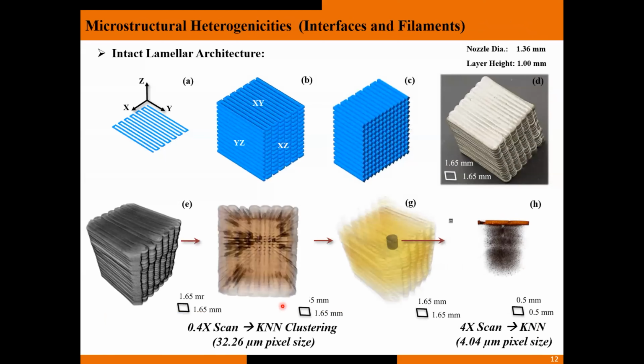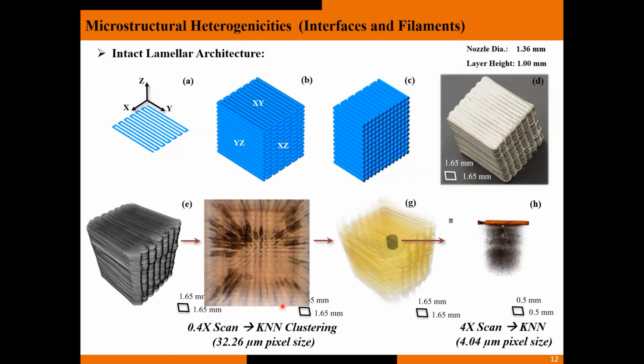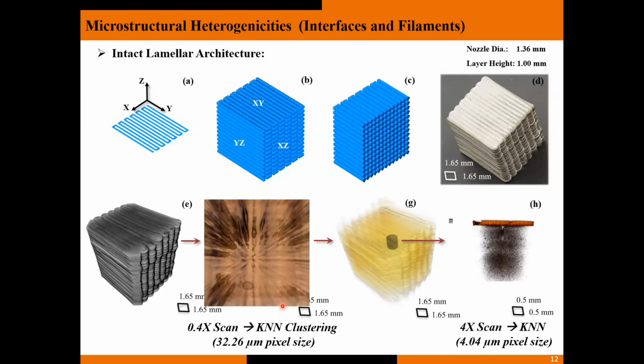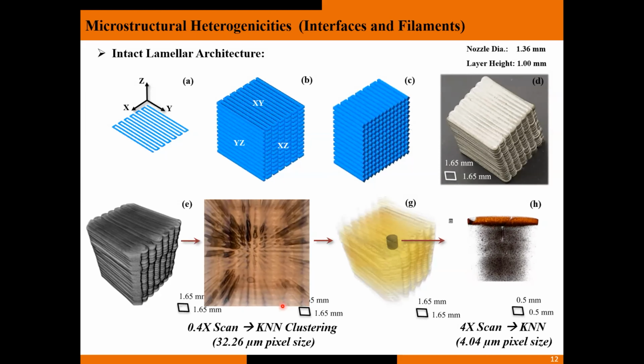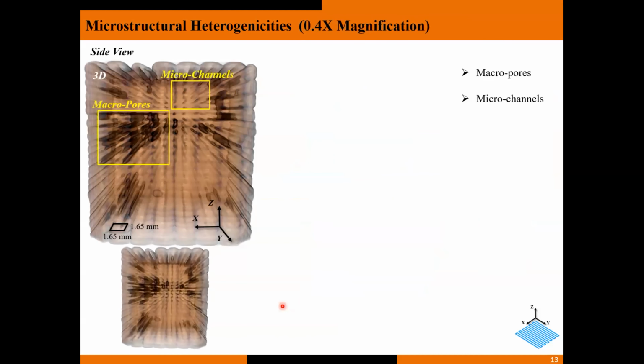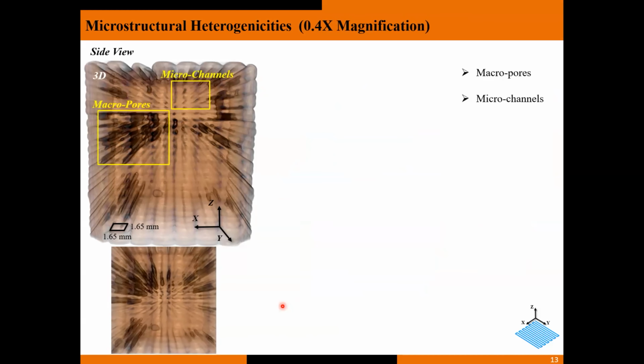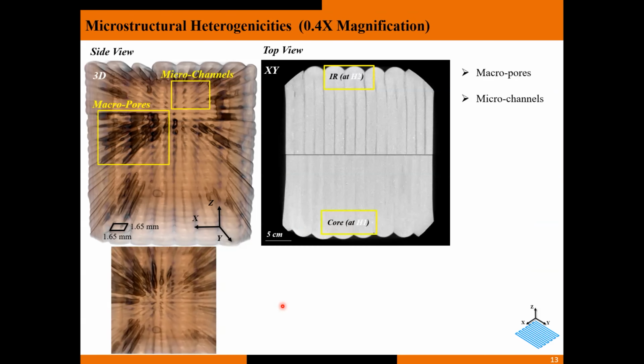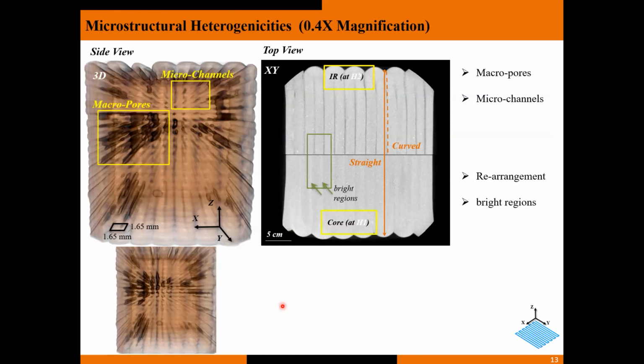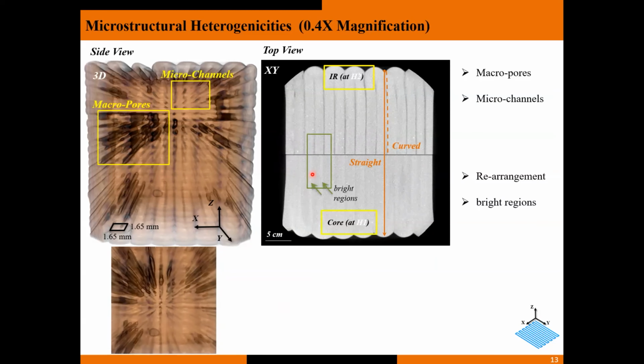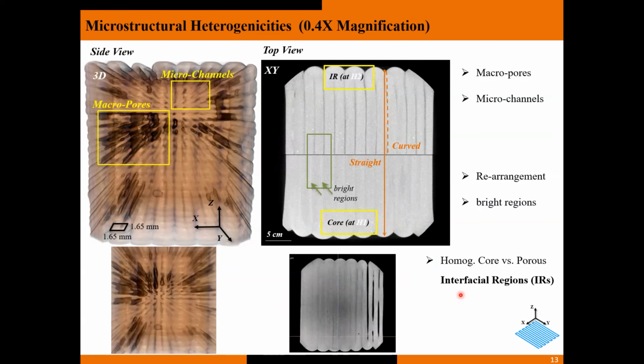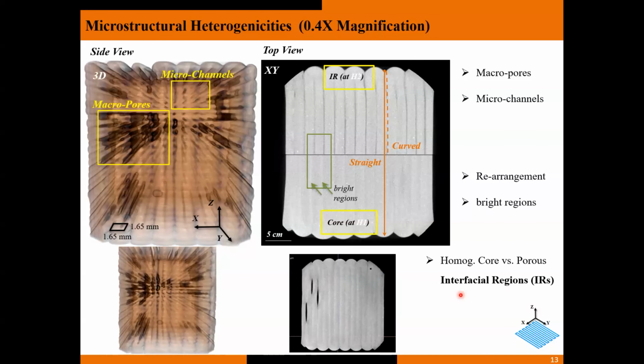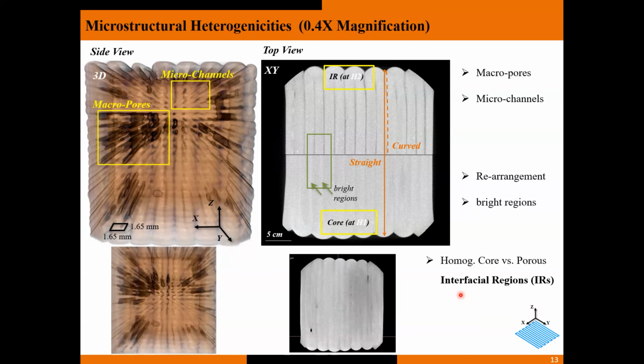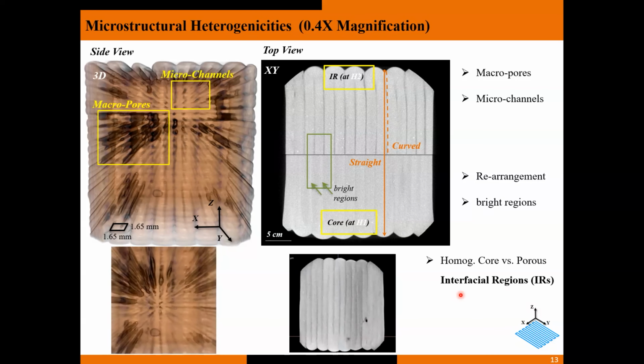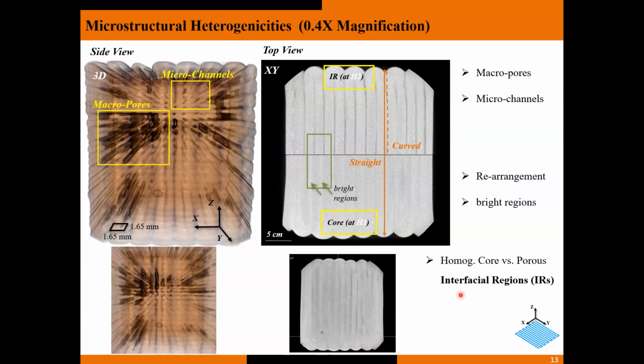In terms of going back to the microstructural heterogeneities, we looked into microstructure of 3D printed cement paste at two different scales at about 30 and 4 micron resolution. What we found was that there are macropores that happen throughout the printing process due to inconsistency, but there are also microchannels that are essentially trapped air in between the filaments. There are two other discoveries that we had in terms of filament rearrangements from a straight path, but also these bright regions, which later we found through a smaller scale characterization that are nothing but accumulation of higher degrees of unhydrated cement grains near the pores, near the microchannels. And so we clearly understood there is a homogeneous core versus a porous interface.